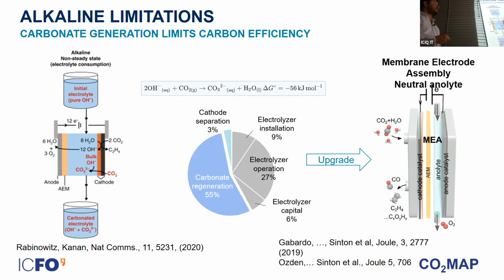It turns out that the reaction where CO2 interacts with the hydroxyl groups that are present in this very alkaline media is downhill. So whenever you mix CO2 and hydroxyl groups, you end up having carbonate. So when you look at this approach at the system level, it turns out that if you want to recycle the electrolyte that would have turned into carbonate, you would use much more energy than you would need to just run the whole operation. So you are using more energy to recycle the electrolyte that has been consumed by converting CO2 into carbonate than the actual energy that you are using to convert CO2 into any molecule of your choice. And this is because we operate in very high alkaline conditions.